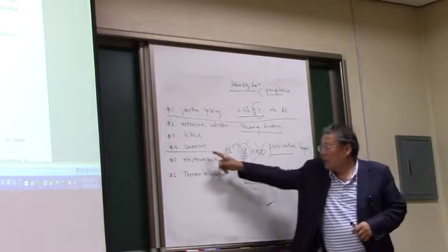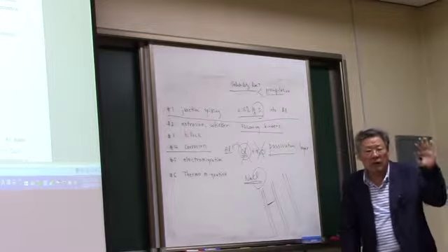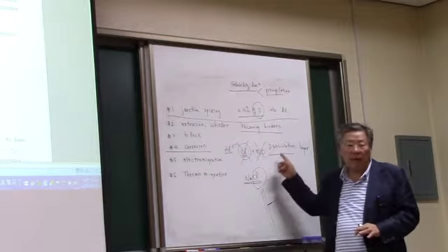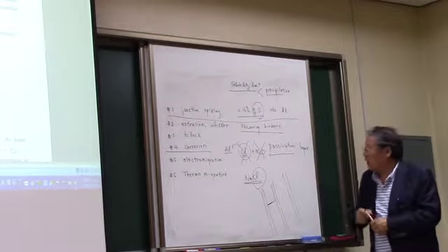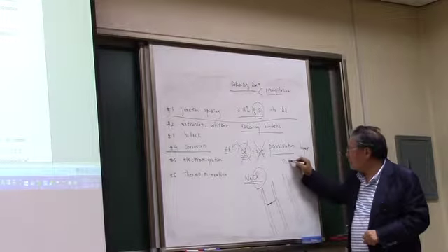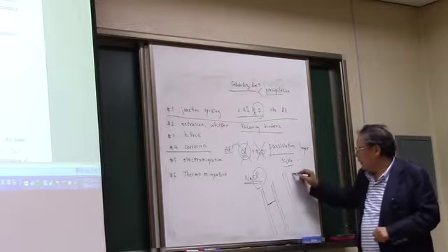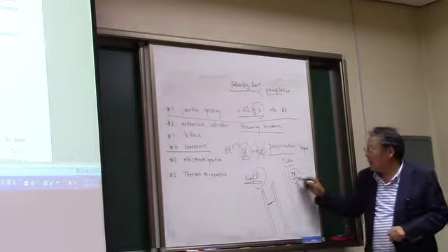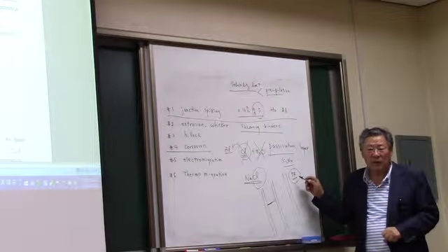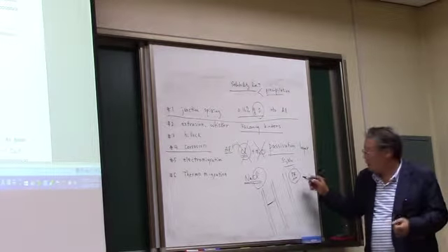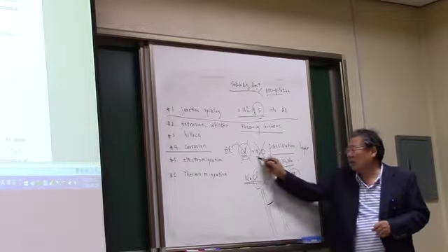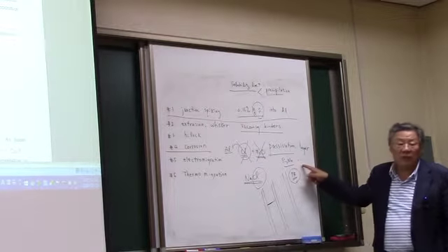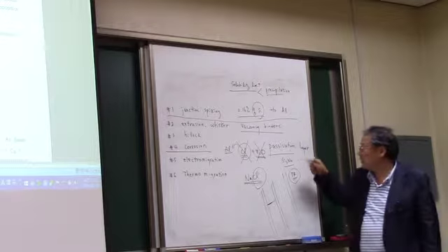Okay. So to prevent corrosion, you are going to have a very clean room to manufacture the device, and you are going to have a very good passivation layer like silicon nitride and so forth. PR is usually used for the passivation layer because it is easy, but PR is not good enough. It's like a vinyl. It is not good enough to completely cut off the moisture. So these days, nitride is the most common passivation layer.